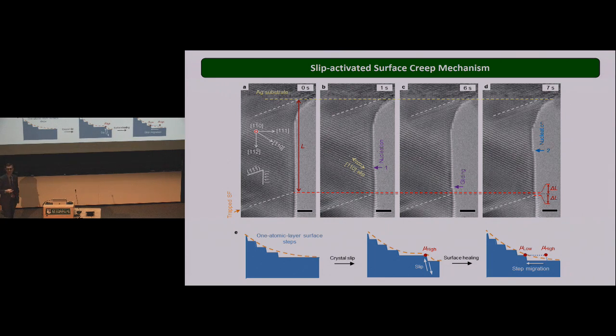On the atomic scale, which is why my talk is entitled Small Scale Mechanics, you need to really be very careful about the atomic scale mechanics happening on surfaces or interfaces. In this example, a dislocation nucleates and leaves a step. It's just one atomic layer high, but it locally changes the chemical potential along the surface. So the material naturally will produce diffusion to reduce the chemical potential locally by displacing these steps near a curved feature on the wire. And that's consistent with the observation here. So we call this a slip-activated surface creep mechanism, which was never observed before.